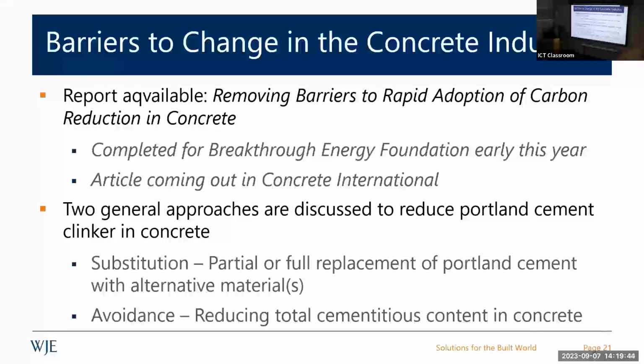In that report, we spent a lot of time talking about the barriers. And briefly, I'll mention the barriers are not what you would think. Our initial approach was that the barriers were going to be the specs, the code. The barriers are risk. That's where the barriers lie. If we change something, who's going to bear the risk of that change? And take out life safety, right? We're not going to compromise life safety, but if I make a change and a DOT says now, hey, we're going to take 50 pounds of cementitious out of our mix, the one who bears that risk now is the contractor, right? The risk falls on the contractor, and the contractor's going to do one of two things. They're either not going to bid it, or they're going to bid it at a really high price. And so that's where you come to.